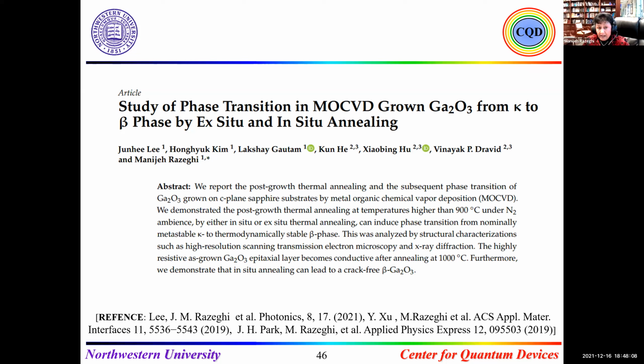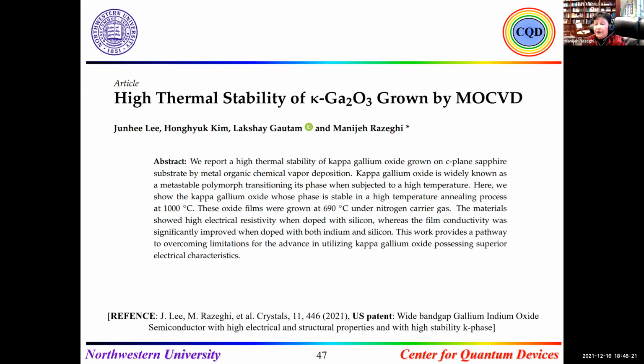We find out that when we do exactly as I explained, in situ or ex situ annealing, we have kappa convert to beta phase. But we found that if we grow under nitrogen carrier gas, when we anneal at 1000 degrees, it remains kappa phase, and we have a stable kappa phase, no change. But with nitrogen, at the same time, the growth rate decreased a lot, because sending nitrogen to the organometallic is not very efficient.